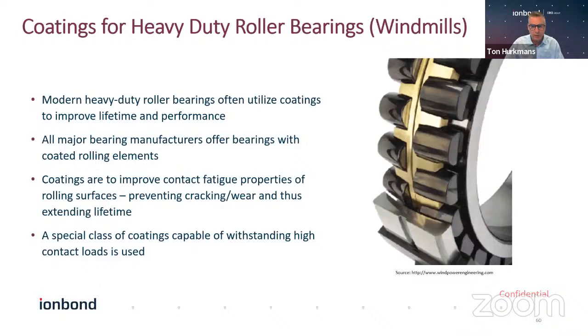Here's an example of bearings that go into windmills. You see them on the right-hand side. There's a roller bearing. These are huge components. They are tens of centimeters, because the bearings are tall, of course, in windmills. The coatings are to improve the contact fatigue properties in this case. And you don't want to have so-called pitting issues in the tribological system.